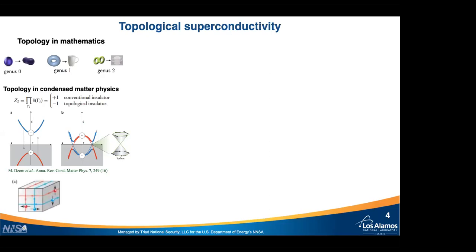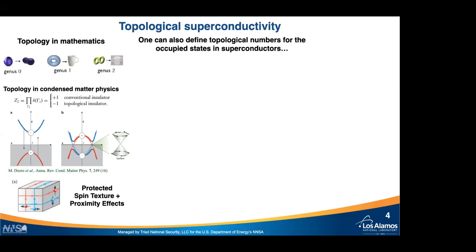And you can envision the surface of a material with spin textures on its surface. Because this spin texture is protected by this particular symmetry of the system, it can be envisioned to be used in dissipationless transport, for example, in spintronics. Or perhaps the most exciting aspect is to have this topological insulator in proximity to a simple s-wave conventional superconductor, where exotic quasi-particles called Majorana fermions may exist. And another class of materials in which these exotic particles could also exist are topological superconductors.